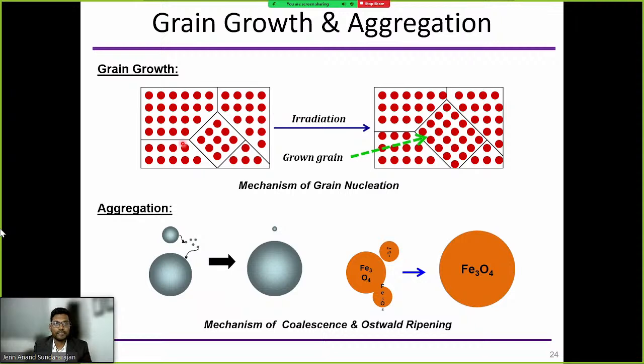When we saw the basics of radiation, basically the electrons, when the ions hit, the atoms get dislocated. And as they get dislocated and heat kicks in, they slowly start to migrate and form bigger grain boundaries. So you can see radiation and grain growth. The fundamental thing happening underneath is basically the migration of atoms from one side to another side. So it's called the mechanism of grain nucleation that is happening inside the material, and that is causing interaction.